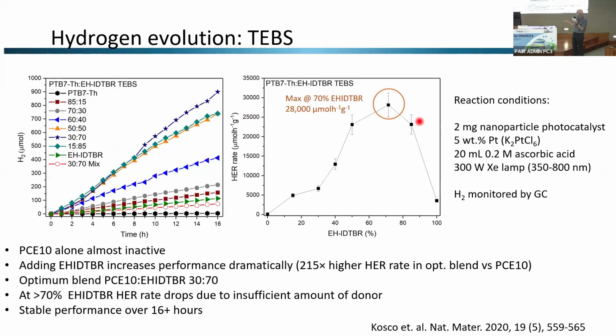So it's now no longer way up here at 90%. We've shifted that to around 70%. So exciton dissociation can occur at the interface of donor and acceptor throughout the nanoparticle. And the other thing of note here is the HER rate. This is an order of magnitude larger HER rate than when you have the core-shell nanoparticle. So having this intermixed morphology, where we're creating all these free charges that can then directly diffuse to the surface and undergo both oxidation and reduction reactions, you can see here that this is a very efficient situation. And these numbers were very, very high at the time because this wasn't really done in the literature.